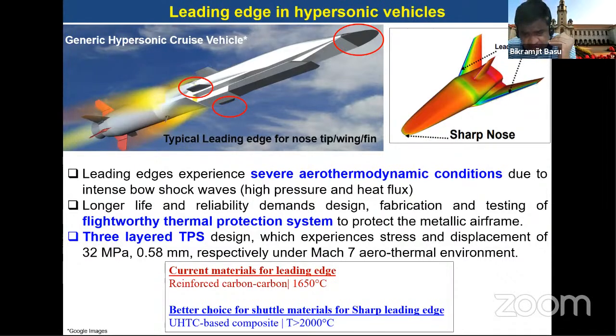And these are the leading edges, which also experience severe aerothermodynamic conditions of high temperature, pressure and heat flux. All the current materials which are used, like ceramic matrix composites or reinforced carbon-carbon composites, have a temperature capability of 1650 degrees Celsius. And a better choice, we believe, is certainly ultra high temperature ceramics, which can sustain temperatures of more than 2000 degrees Celsius.